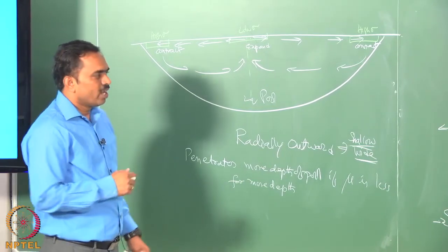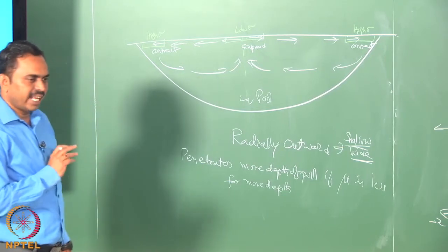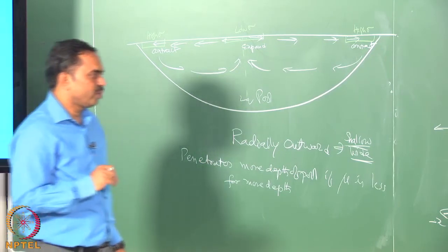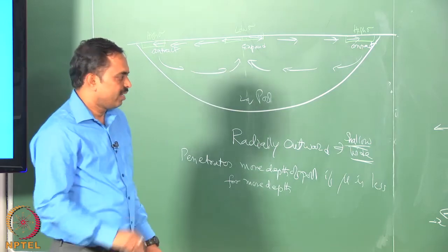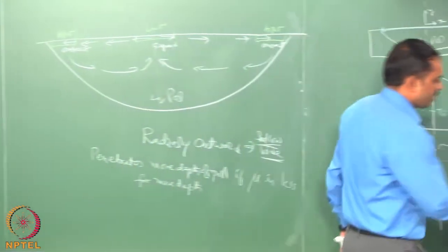The magnitude of the surface tension driven flow we can estimate using a small scaling analysis, which I would discuss in a tutorial session later on, and that would come out to be about a meter per second. Okay, so, magnitude.